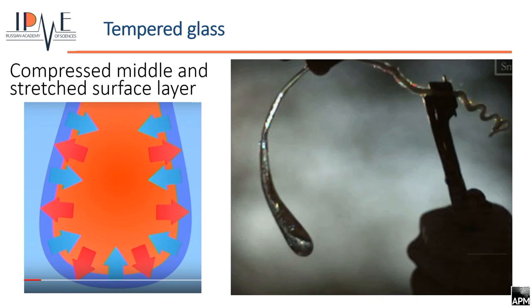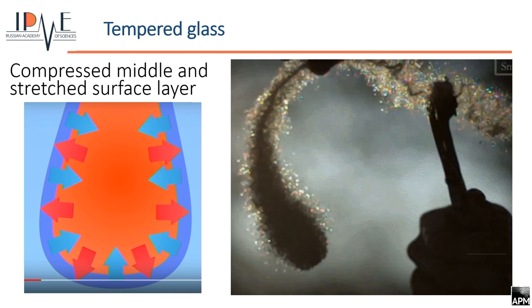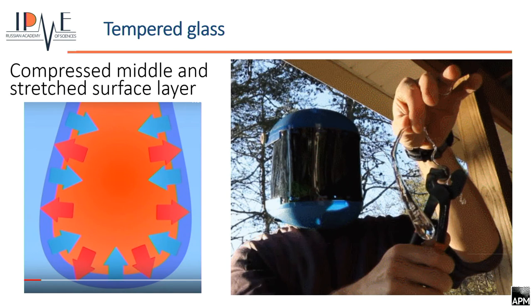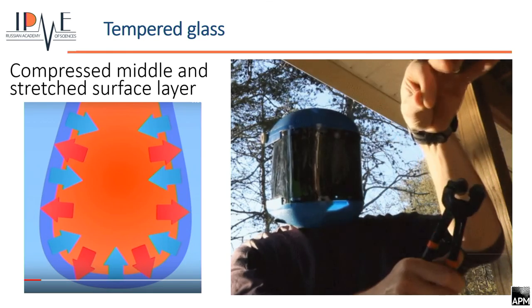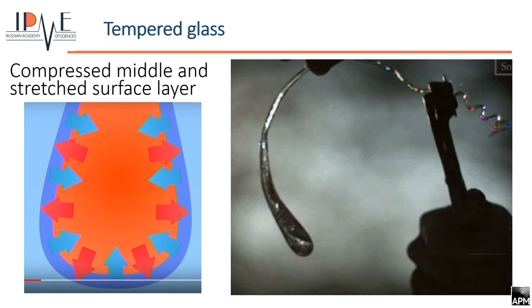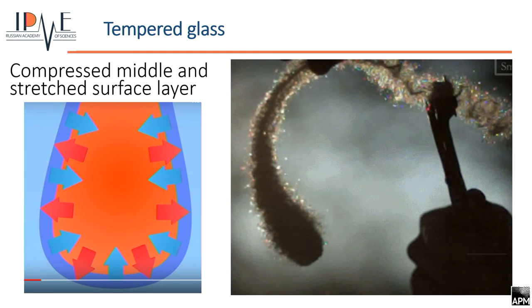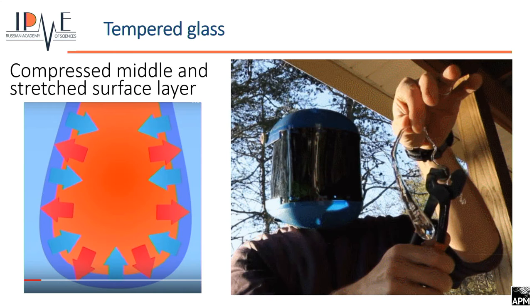because in these drops a very thin surface layer is formed, with thickness approximately 500 micrometers, in which we have a stretched layer, and in the middle of the drops we have compressed glass, and this unique situation leads to a very much higher influence of the surface layer on the properties of such glass. It is very important that glass is an amorphous, non-crystalline material, but stones from lava are crystalline material.